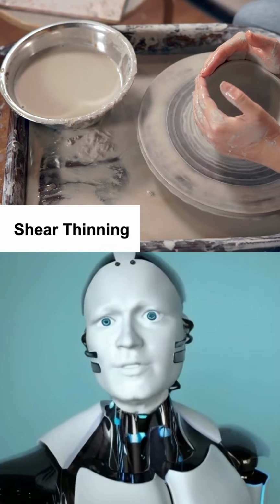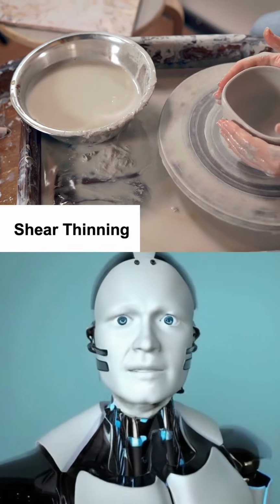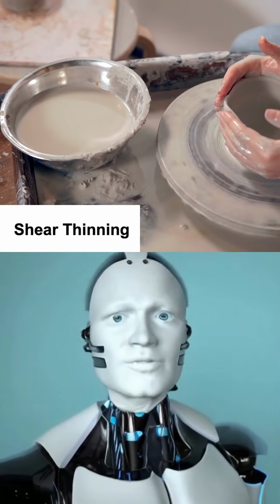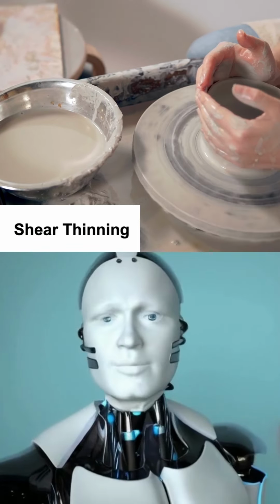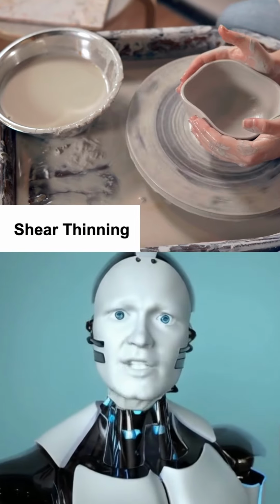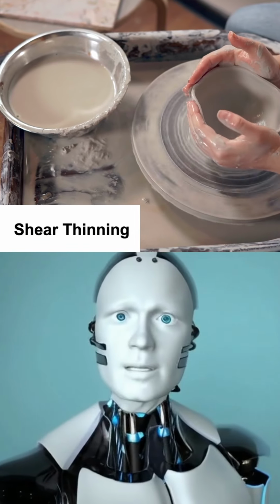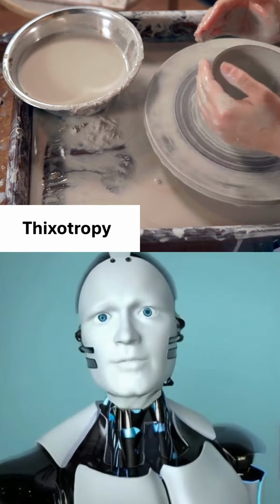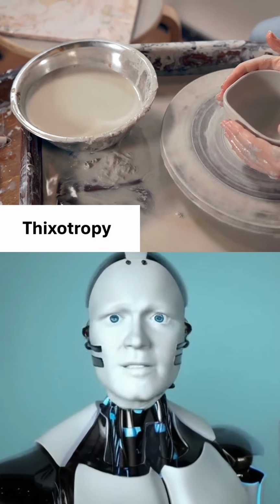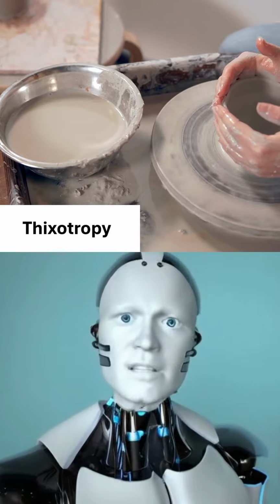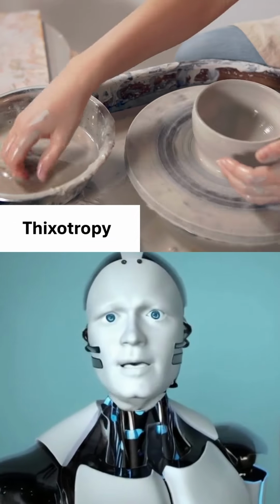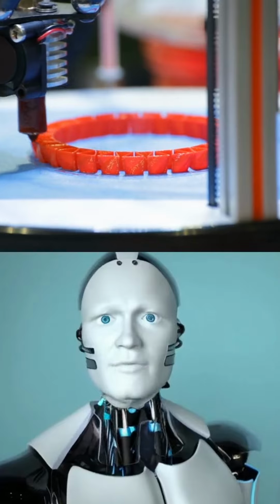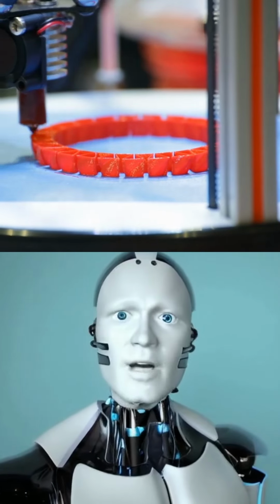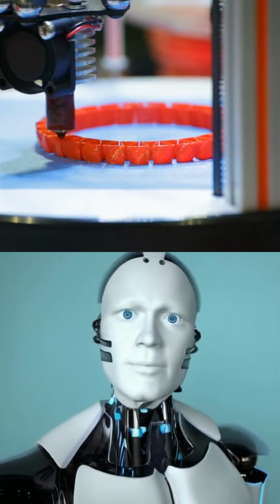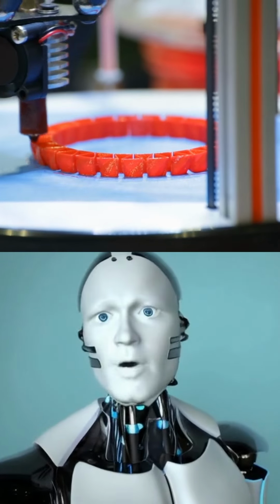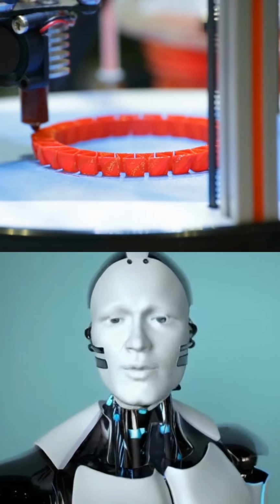But when that pressure force disappears once the material is on the build plate, the viscosity of the material returns to its higher undisturbed value, which prevents it from flowing, which helps it keep the intended shape while cooling and solidifying. A related property is known as thixotropy, which characterizes how fast a material will recover its viscosity once the shear force is removed. Ideally, you want the viscosity to recover quickly so that the current layer will solidify before it's time to print the next layer on top of it. Other important properties are material yield stress and viscoelasticity.